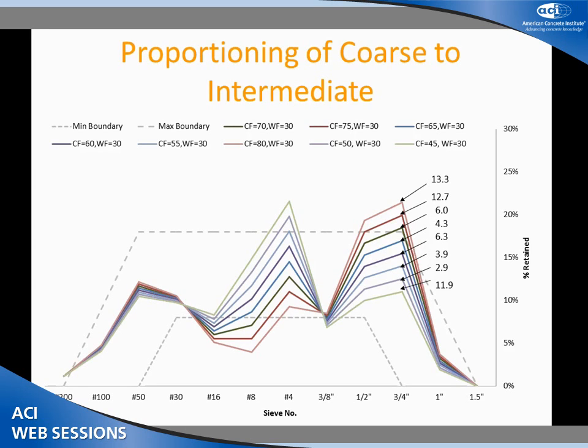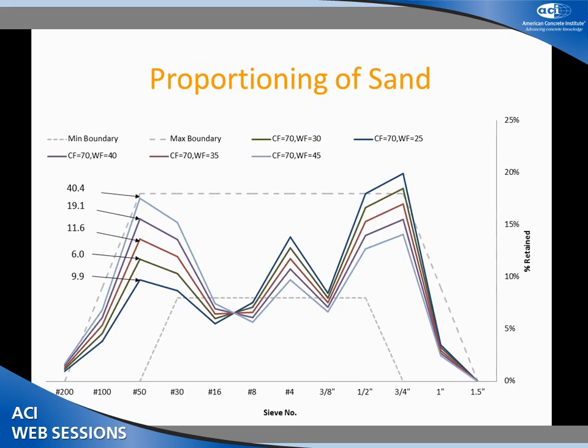Let's start to really unlock some of the mysteries of optimized graded concrete. Let's take mixtures with sand contents being the same and start teeter-tottering: almost 100% large aggregate with almost no intermediate — we needed 13.3. We reduce the large and increase the intermediate, over and over again. What do we see? We go from high, to lower, to lower — we found a sweet spot — and then high again. We found a boundary that bounds the performance.